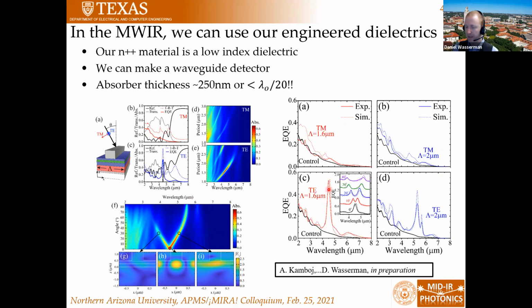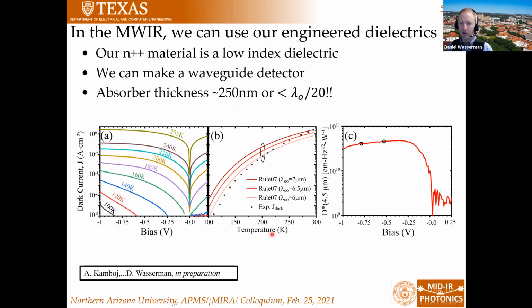When we look at the device that has the doped semiconductor, essentially that has this waveguide, we can get over 50% external quantum efficiency in this really nice narrow peak, compared to our control, where we're only getting about 10% absorption, right? And so this is a guided mode resonance that we're leveraging here. And so we can tune that by controlling the grating and the angle of incidence and these sorts of things. And most importantly, we can do this in a detector absorber that's only 250 nanometers thick.